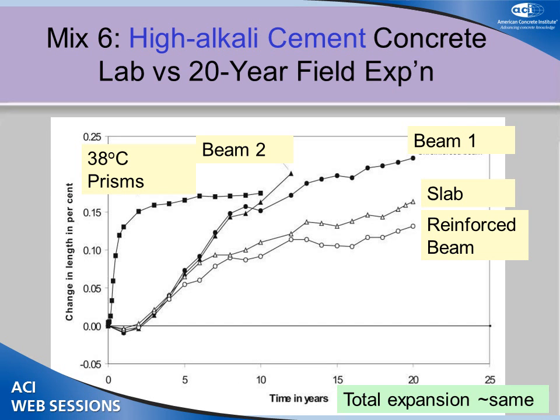So just to compare, we took the high-alkali Portland cement because it had the highest expansion. If you compare what happens in the field versus the lab here, the 38-degree concrete prisms, the one on the left expanded faster, and the two unreinforced beams, beam 1, beam 2, reach about the same expansion at the same age, but they just took longer to get there. And the reinforced concrete beam and the slabs on grade were somewhat lower than that. But they're in the same order of magnitude of expansion, because people complain that the 38-degree concrete prism test is accelerated and you wouldn't get that in real life.